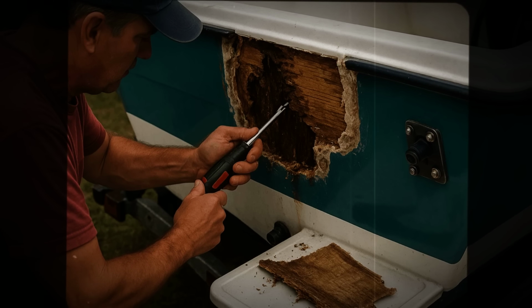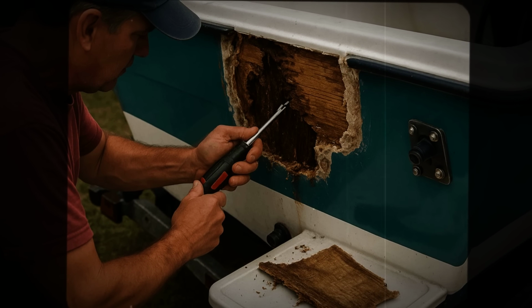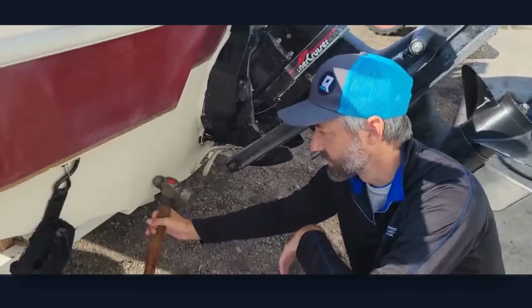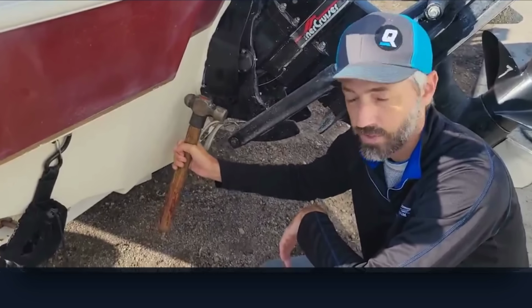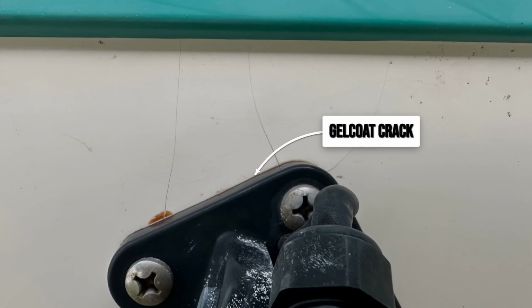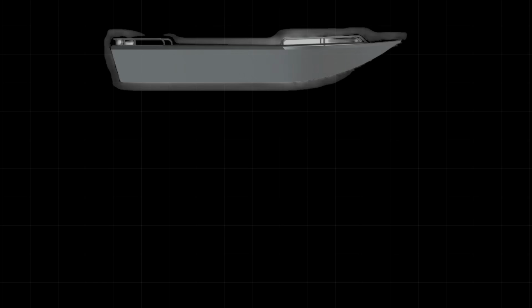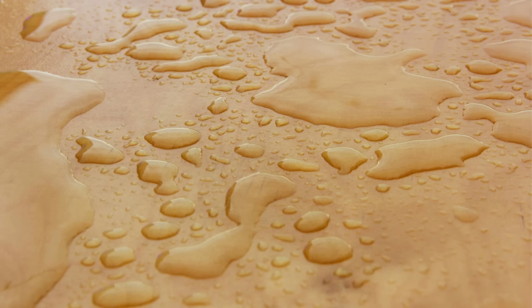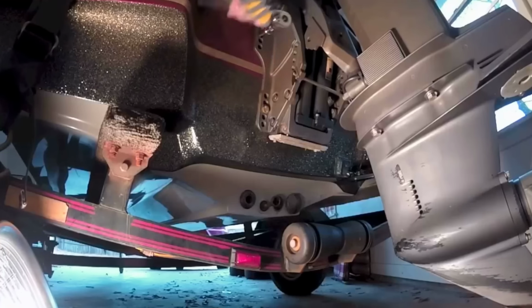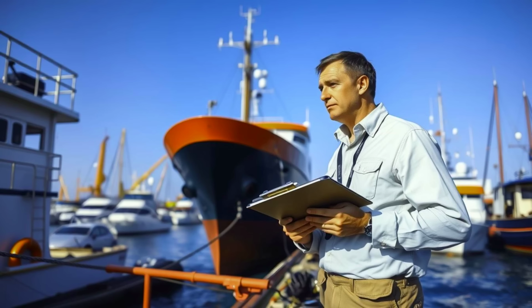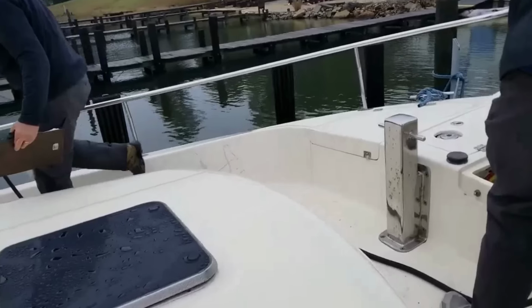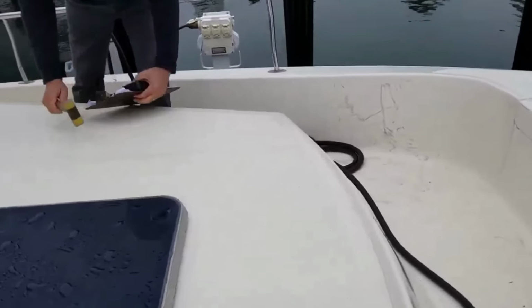Most fiberglass boats built before the 2010s used marine plywood inside their transoms, stringers, and deck cores. 1 unsealed fastener hole, 1 gel coat crack, and water is behind the laminate, working against wood you cannot see. The hull looks fine right up until the deck flexes underfoot, or a transom fitting starts backing itself out. Marine surveyors call it the most underestimated failure mode in used boat inspections.